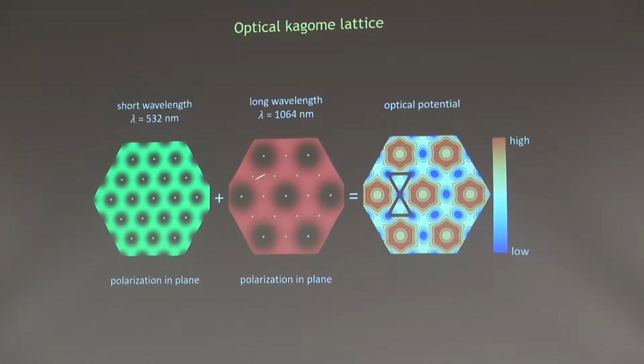And on top of that, we lay another triangular lattice formed by infrared light. And it's positioned so that one of the places where the infrared light intensity is 0 coincides with a place where the green light intensity is 0. And the effect of that is the following. The red light actually attracts atoms to its higher intensity spots. So if I look at the overall potential that's produced, you see that there used to be 4 sites within a unit cell of the lattice. One of the sites is increased in energy and excluded from the physics of the problem. And the remaining 3 sites, which are labeled here in blue, are equivalent sites, and they form the sites of the Kagome lattice. So you see here 2 of the plaquettes of the Kagome lattice.